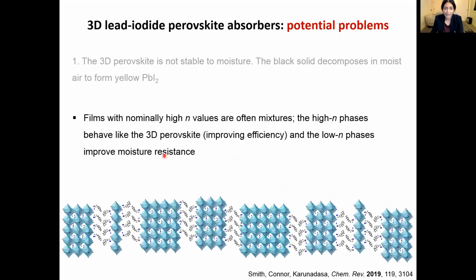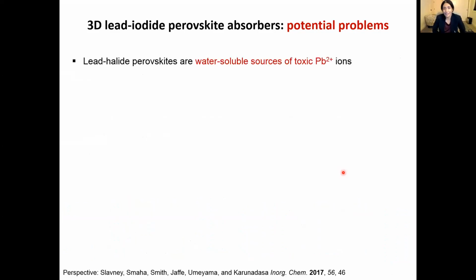It's important to remember that in these films, especially with high n values, we are almost always faced with a distribution, which is kind of interesting to think about. So the large n values basically act like your 3D perovskite, absorb sunlight, generate current, and the small n values bring with it more organic groups and repel moisture. So we were fairly pleased with this result that you can now form perovskite devices out in air, but it wasn't entirely satisfactory because we knew that both 2D perovskites and 3D perovskites contain a water-soluble source of lead. So these materials are toxic sources of lead, and the toxicity effects are compounded by its water solubility.